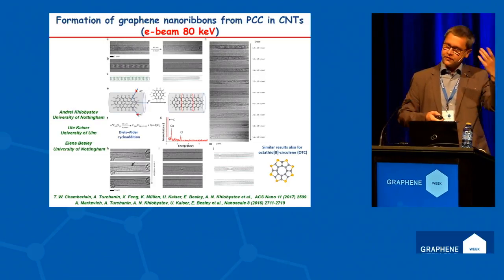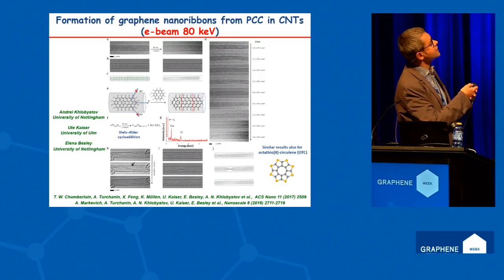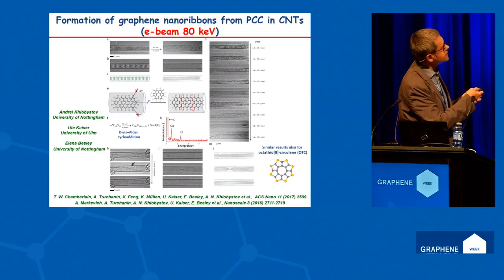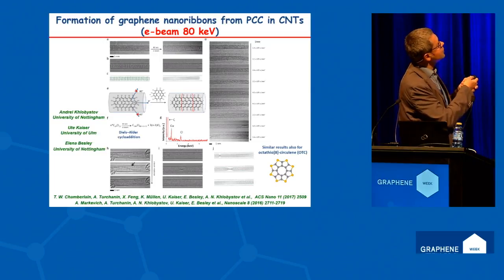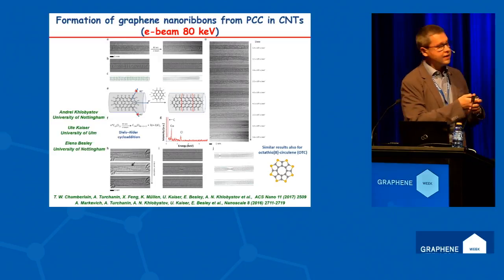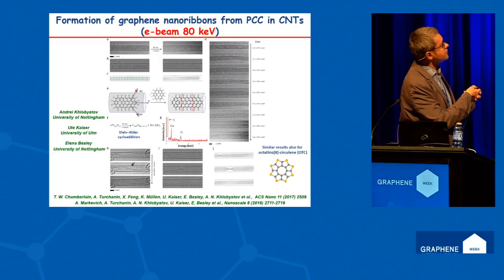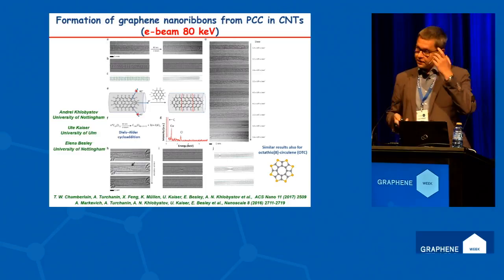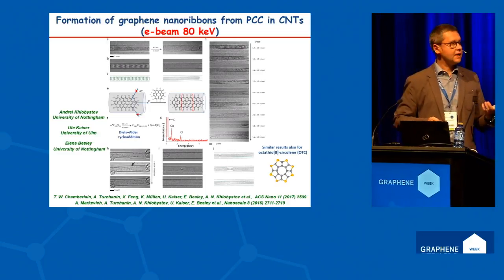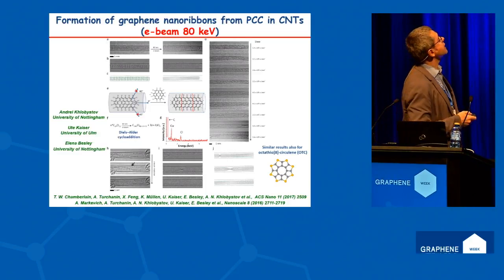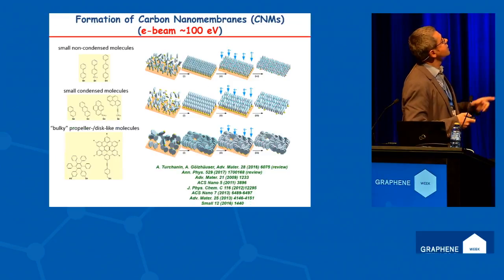If you start to irradiate these carbon nanotubes with electrons, you see some transformation. If you follow this transformation very precisely, you can see that these individual molecules are fused together, forming a graphene nanoribbon, which can then be imaged here. This is an example of the interaction of high-energy electrons with matter.